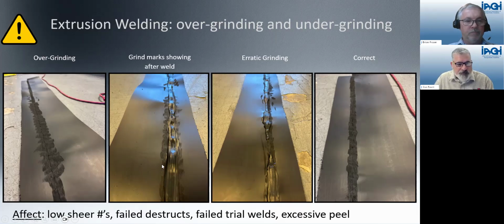If you look at the very end of that picture, you can see they straightened it out, which looks proper. And the second picture from the left on the right shows an illustration of the grind mark showing after the weld, improper welding position with the extruder, which is too much extrudate on the liner, and or all of the above. The next picture on the right is just erratic grinding, erratic welding, too fast, too slow. It's exaggerated, I get that, but this is what you do not want to see in the field.